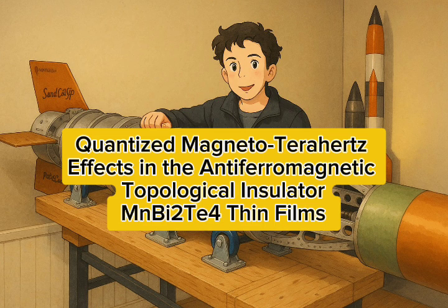It showed a beautiful three-stage behavior mirroring the magnetic transitions. At low fields in the AFM state, the calculated GHC was essentially zero. In the intermediate canted AFM state, 2-4 Tesla, GHC became finite, but was clearly below the expected quantized value. Right. But then at high fields, 5T and above, where they saw the saturated Faraday rotation, the calculated GHC also saturated, right around 0.9 times e²/h. 0.9 e²/h. That's incredibly close to the magic value of 1 e²/h for the Chern insulator state.